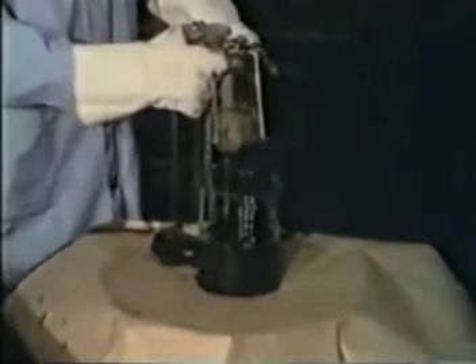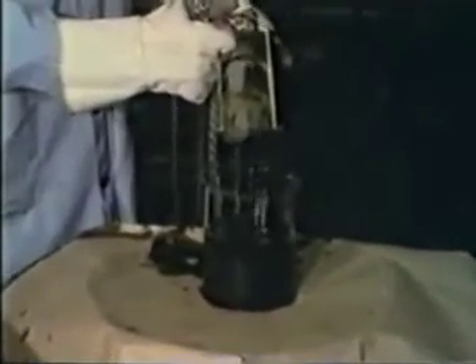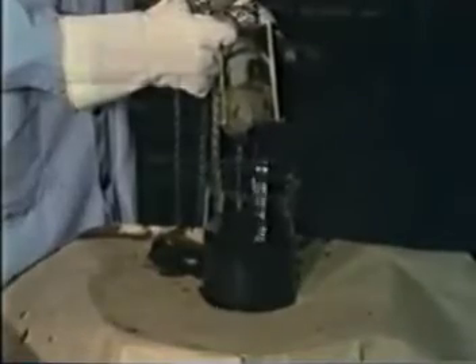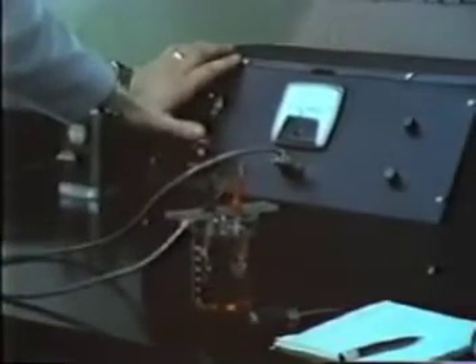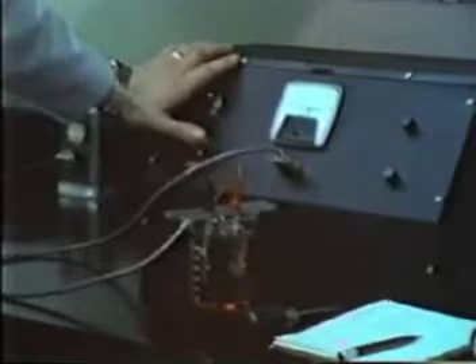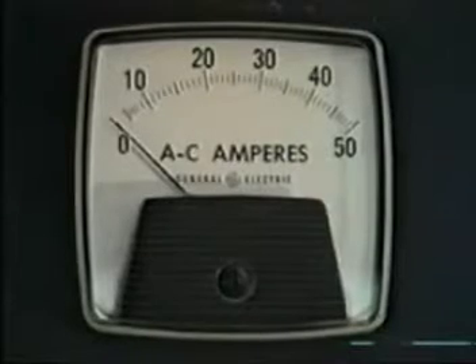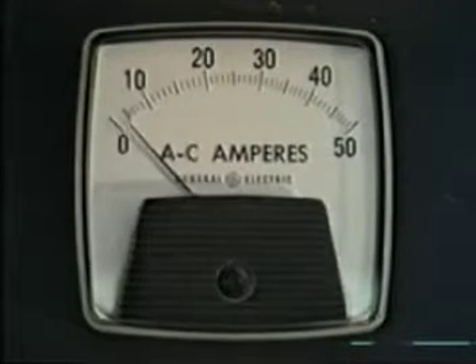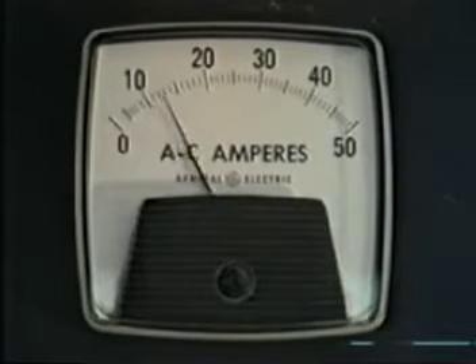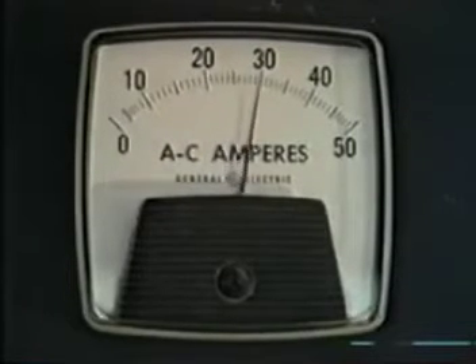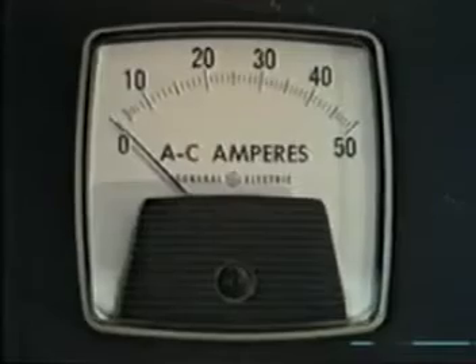Because of the continuing breakdown of quench oil during use, its ability to extract heat must be constantly monitored. This is accomplished by means of a hot wire test, which measures the amperage required to melt a wire that has been placed between two terminals and then submerged in a beaker of the oil being tested. The power is then gradually applied until the wire burns out. The oil's quenching speed varies directly with the amperage carried by the wire.